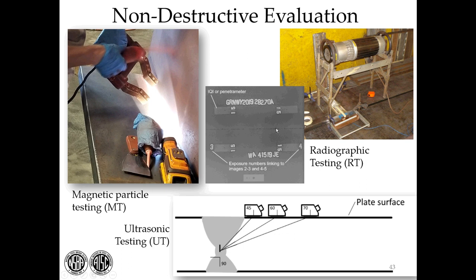If this was a 3-inch plate and you saw that, you wouldn't know if you were near the surface or at the root or on the far side. With UT, you can tell. That's a very nice thing about UT. And typically if a fabricator does encounter this situation in a radiograph, before the fabricator fixes it, it'll go back and check the depth using UT.